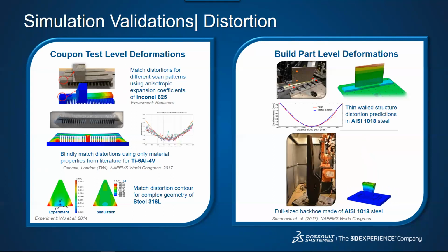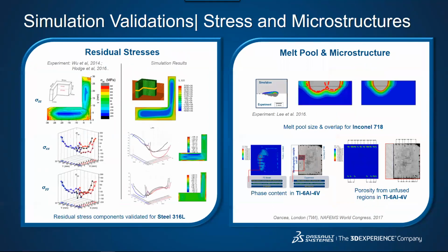And then we can move to looking at things like this full-size backhoe, which takes a week to build and 6 hours to simulate. So there's some clear value there in having validated simulation capabilities. We're also the first process simulation software to validate residual stresses induced by the AM process. We've compared this with some experimental residual stress results reported in literature for this L-shaped column for stainless steel.